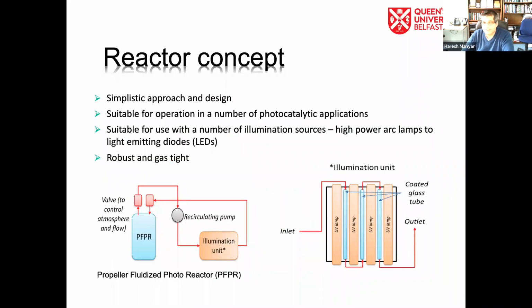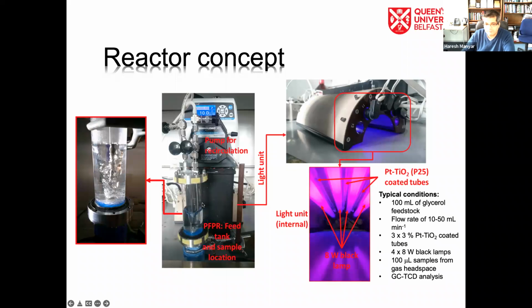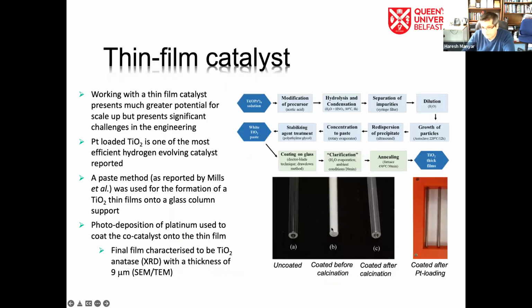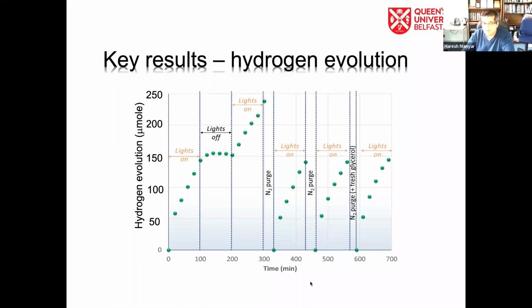So for that, again, we have another continuous flow type of reactors where we have got the tubes which are coated. As you can see, we have got both batch reactors here and continuous flow reactors here. In the continuous flow reactors, the tubes are coated from inside. You can see on the screen here, the quartz tubes are coated with titanium dioxide and then annealed, it becomes transparent. These are supported with platinum nanoparticles throughout the tube. These are transparent tubes, can be very efficiently used for photocatalysis. And this is the example of hydrogen evolution.